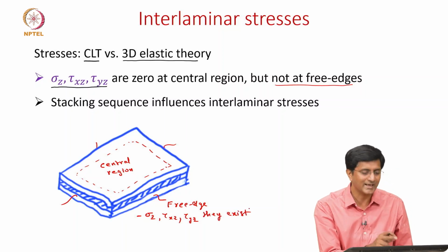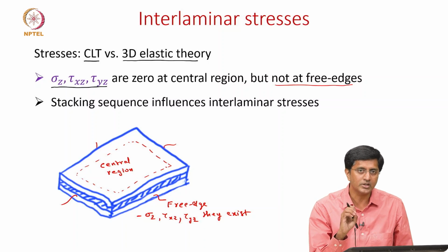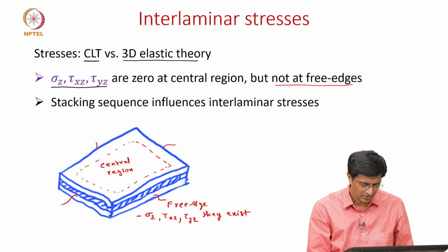According to the classical laminate theory, we said that there are no out of plane stresses. But if we look into the 3D stresses, which come from either theory of elasticity or 3D finite element analysis, we notice that these stresses exist.